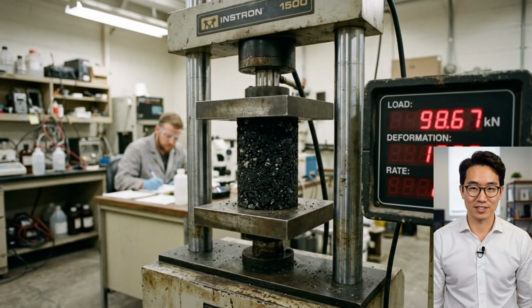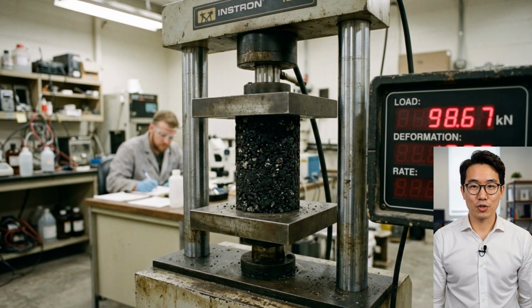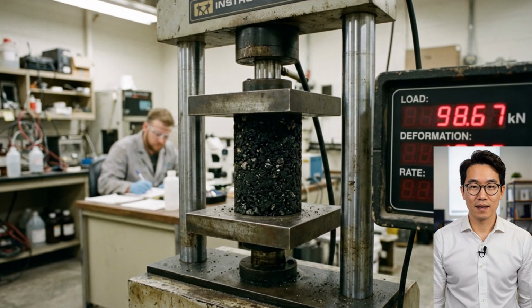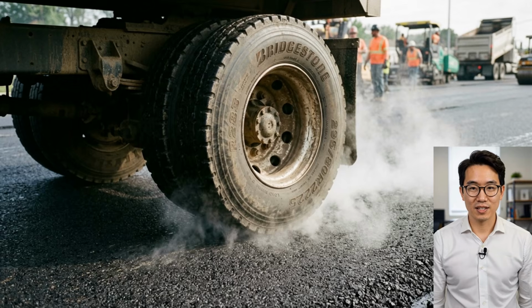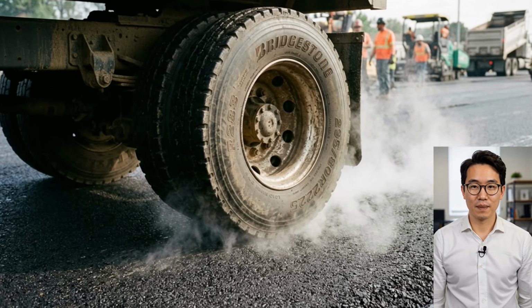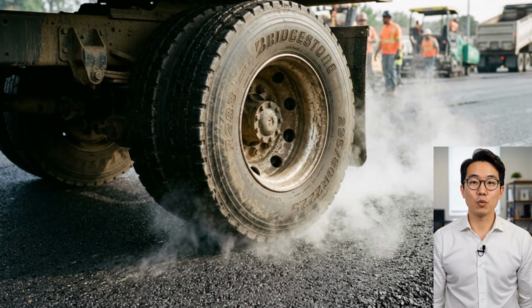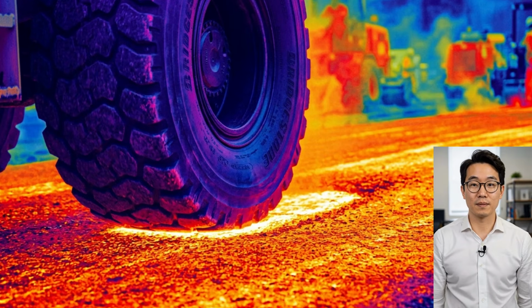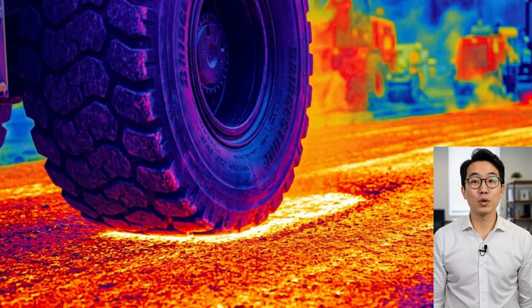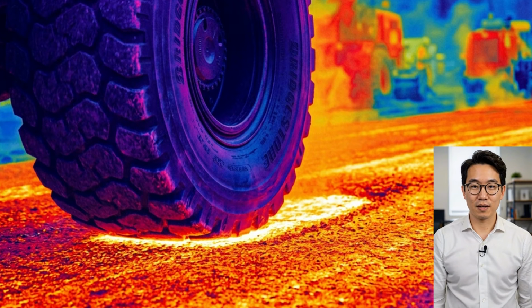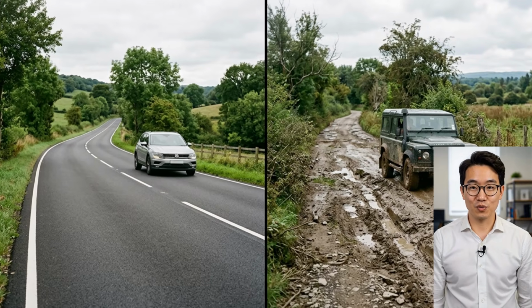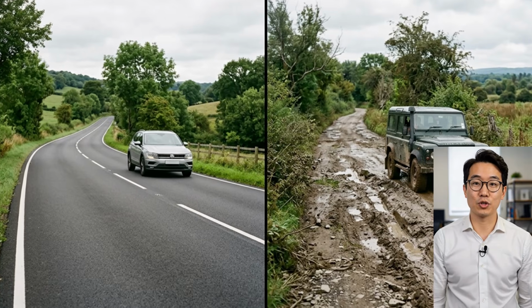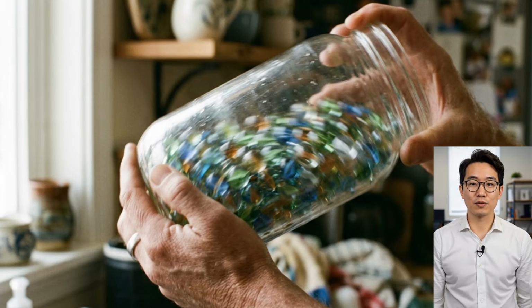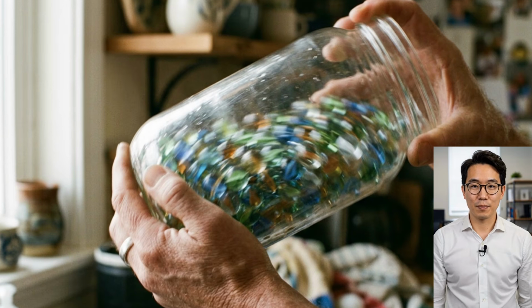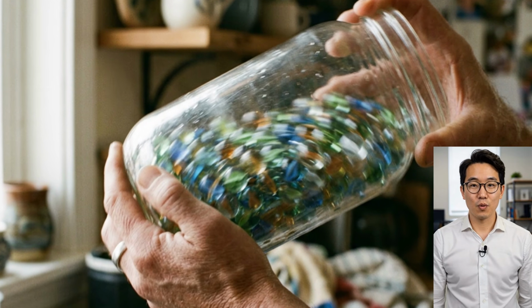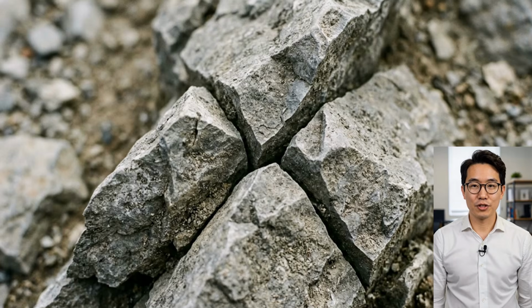Chinese researchers started testing this with real numbers. In a 2022 study from Chang'an University, engineers replaced part of the natural aggregate in asphalt mix with steel slag. They found a strong result when 60% of one key stone fraction was replaced. The dynamic stability of the pavement mix rose from 3,947 to 5,732, which meant the road resisted high-temperature deformation much better. That was a 45.2% jump. In plain English, the mix stood up far better when heat and wheel pressure tried to push it into ruts.